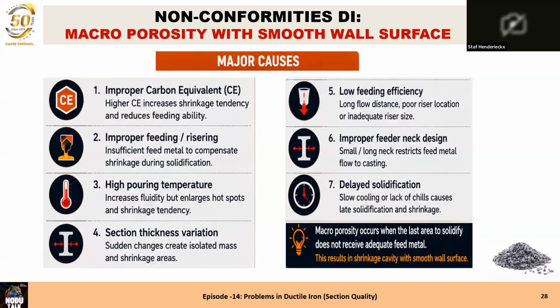Low feeding efficiency: every riser must be calculated concerning the modulus, to make sure it can feed until the casting is really solidified. But the number of risers is also to be calculated, because every riser has a feeding distance, and the feeding distance depends on the size of the section of the casting, but also on the liquid quality of the casting. The nodule count mainly is very important there. If that's not okay, whatever riser can be okay, but the feeding efficiency will not be okay.